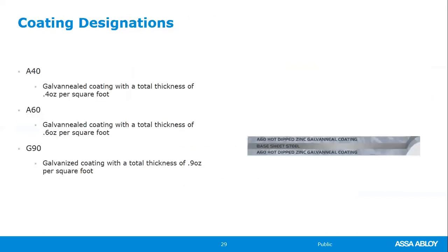Here, it just kind of gives you the coating designation. So we talked about the A and the G, because the G is your galvanized, the A is your galvannealed material. Then we come down to the coating weight. So the A40, the A60, or the G90, basically this is telling you how much zinc per square foot of material you have on both sides of the steel. So on the A40, basically you have 0.4 ounces of zinc per square foot of material on both sides. So you've got 0.2 on each side, making the total 0.4 ounces. A60 is 0.6 ounces, so you've got more zinc per square foot of material.